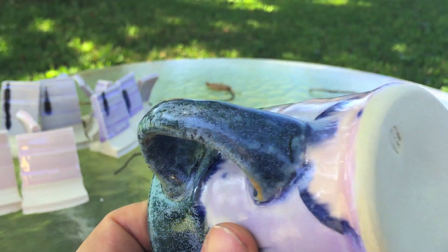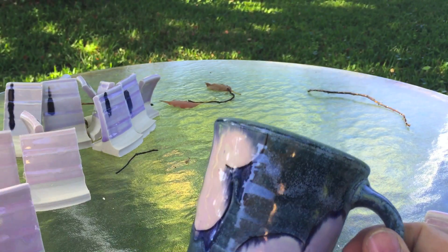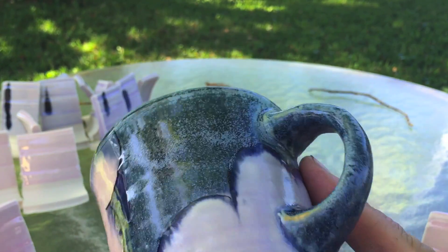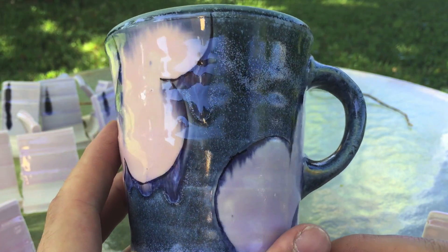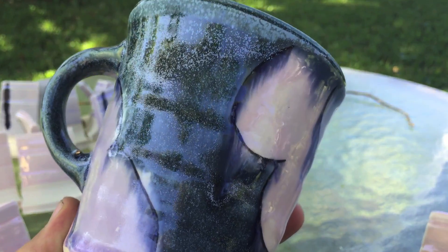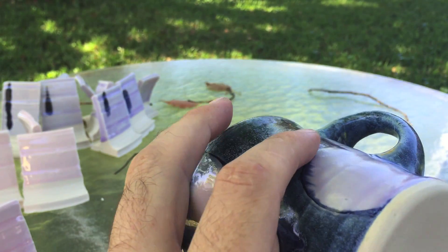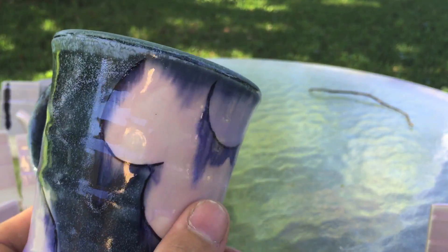Mary's Porcelain is a dirty porcelain — it's got some bulk grog in it. I did not get any pinholing on my test tiles, which are Grawley Porcelain. I tried the same glaze base with copper on Mary's Porcelain and it pinholed as well, so this base doesn't work so well on Mary's Porcelain at Cone 6. The Campana Clear base pinholes. They were bisque fired to 04, slow bisque. Alright, that's my experiment. If you like this, give me a thumbs up and I'll do more on my channel. Hit that subscribe button and I'll make more videos. Have a great day, bye everybody!